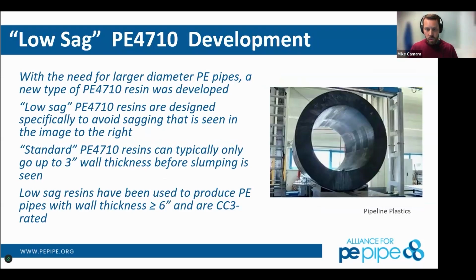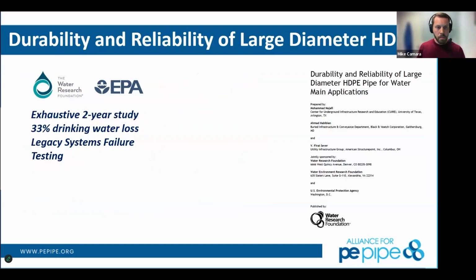And so again, as I mentioned, that's what we're trying to do, is avoid this sagging or slumping that can take place. These standard 4710 resins that we've used in the past, we see them making up to maybe 2.5 to 3-inch pipe wall thickness pipes without many issues. For the low sag resins, though, we see them getting up to 6 inches, sometimes greater, without significant sagging or slumping. And they're CC3 rated, so it meets AWWA requirements for chlorine resistance. It's really impressive what these resins can do in these types of applications.